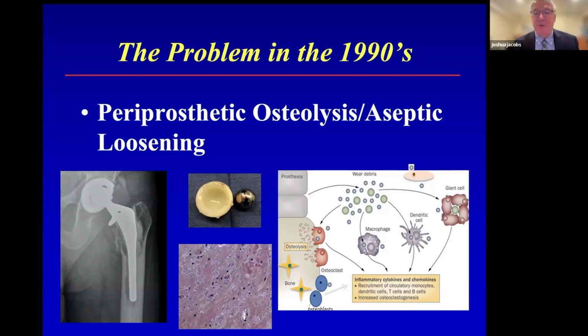So we thought the biology was such that debris generated from wear would interact with local cells called macrophages. This is how the immune system would respond to debris generated from the bearing surfaces, and then initiate a whole cascade where after phagocytosis, where the debris would come intracellularly, this would cause elaboration of pro-inflammatory cytokines, and this inflammatory reaction would interact with bone cells, such as osteoclasts, which cause resorption of bone, and osteoblasts would be turned off, so there'd be less bone formation, more bone resorption, leading to this osteolysis. So this is the way we understood this cascade, and that was driven by the volume of wear debris, the volumetric wear, meaning the amount of wear debris per unit time.